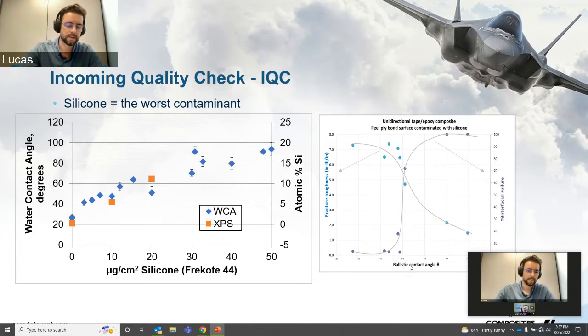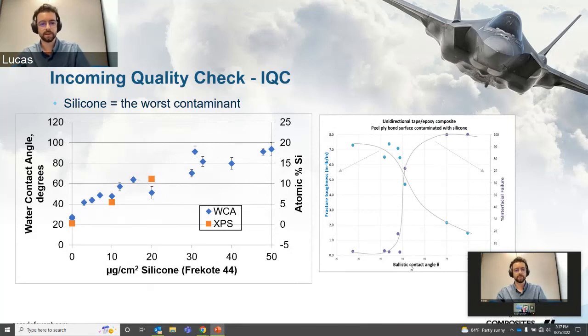All right. I saw Doug Decker was here listening today. He's seen this chart before, and it's a really good one, right? Because what happens is that as we add contaminant to that surface and as our surface energy decreases and our contact angle increases, we see our fracture toughness decrease here. Now you can't see my cursor. From left to right, that's the top curve.